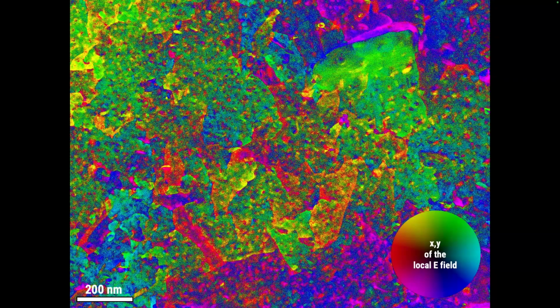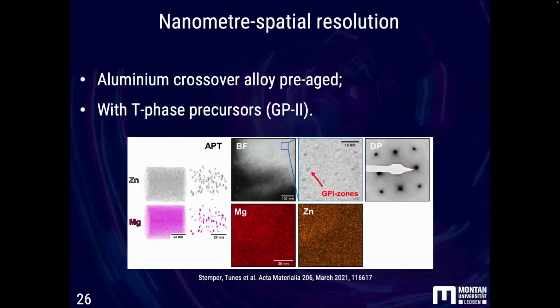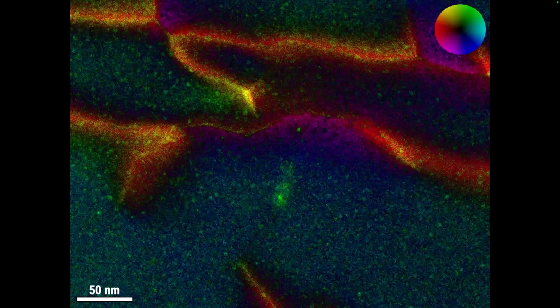Okay, just to show you the potential of this technique to study hydrogen enrichment, I did another experiment, at high magnification with a different alloy. It's a pre-aged alloy, and in the pre-aged condition, instead of having precipitates, we have GP zones, much smaller. With the TEM, we can barely see them. You can barely see them with EDX. Only with APT can you resolve them very well. Unfortunately, we cannot see very well, but we have here dislocations, the matrix, and these green guys here are the precipitates. And this is just the shift of the electron beam.